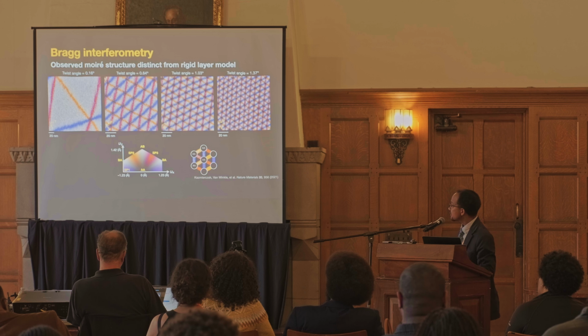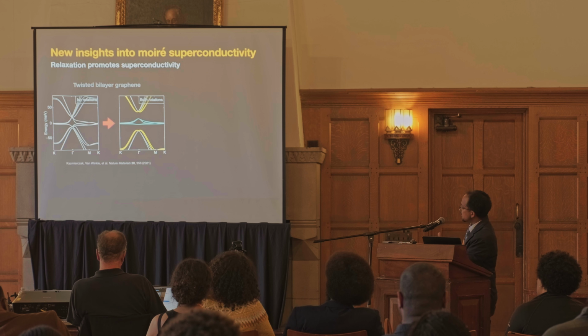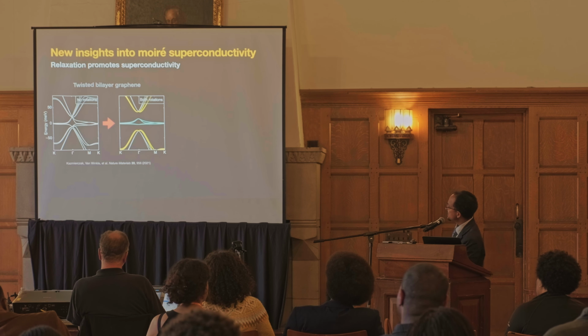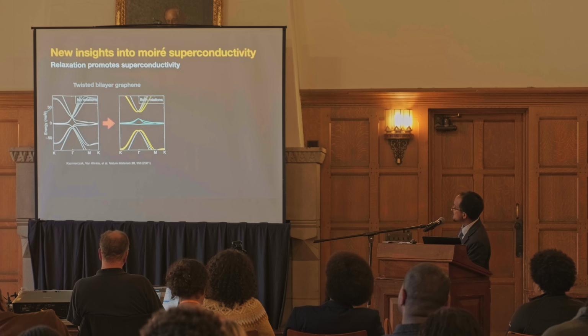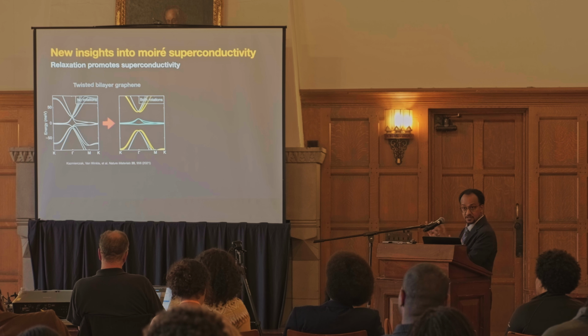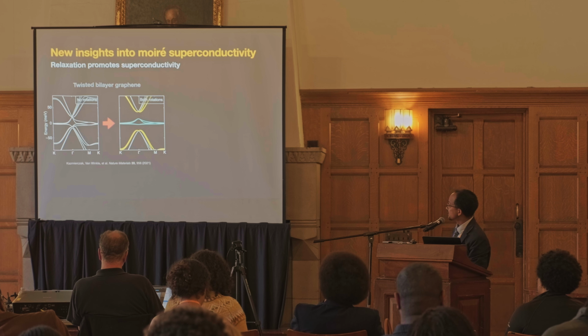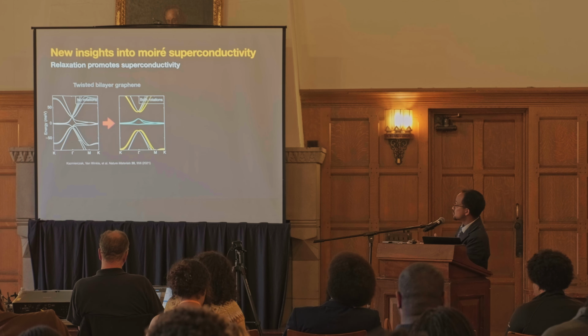All right? And so without going into too much of the details, what we learned from this is called a band structure. It basically tells you what are the allowed energy levels that electrons in the system can occupy. Every crystal is going to have some rules that the electrons in the system have to obey, which dictates the energies that those electrons can have. In this electronic band structure over here, if you assumed that the cartoon was real, this is what you would get. And it would puzzle you, if you were a theorist, to understand how this system superconducts.